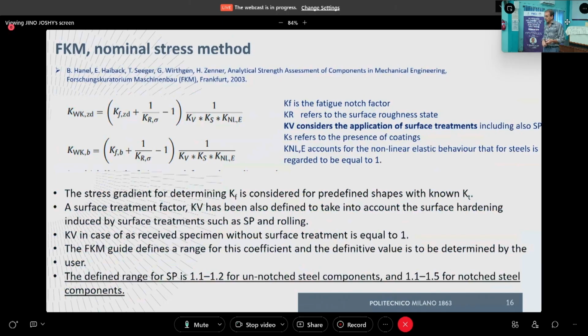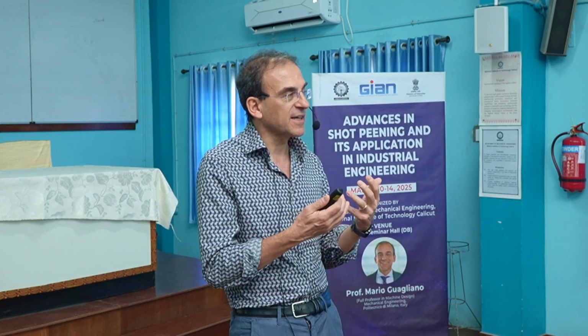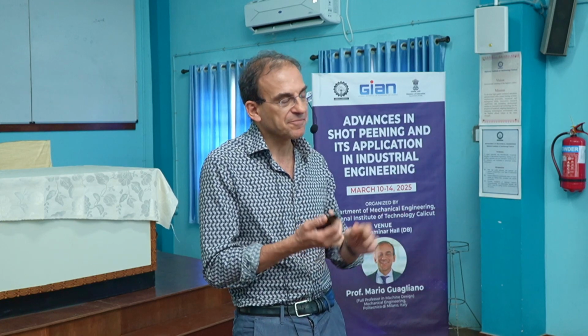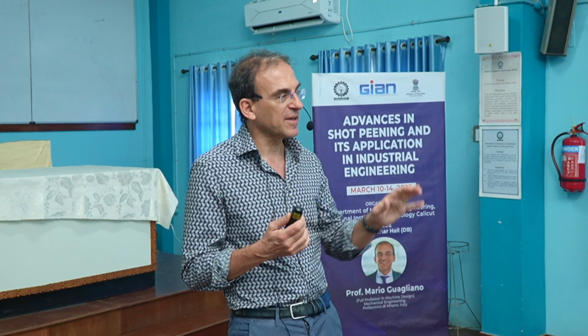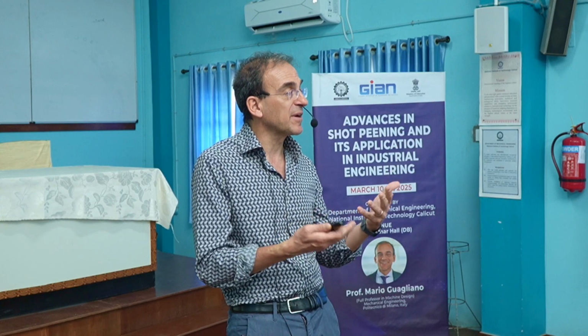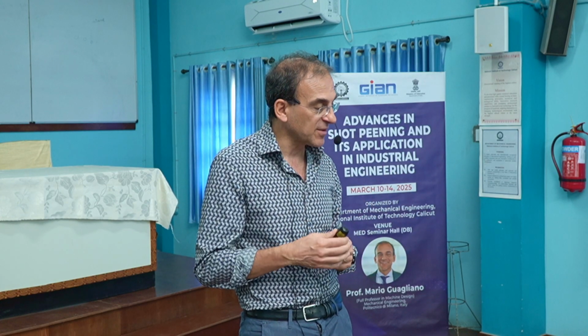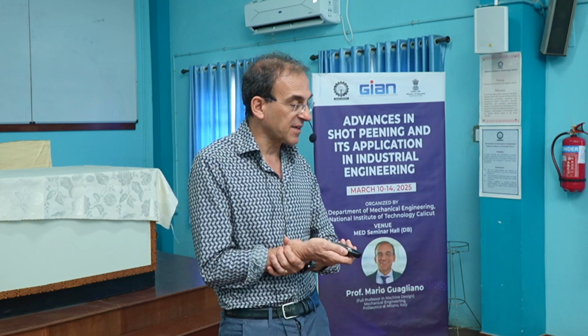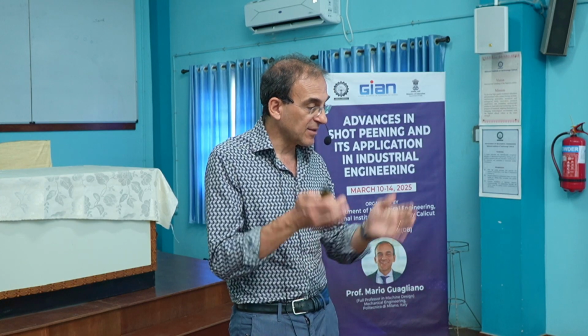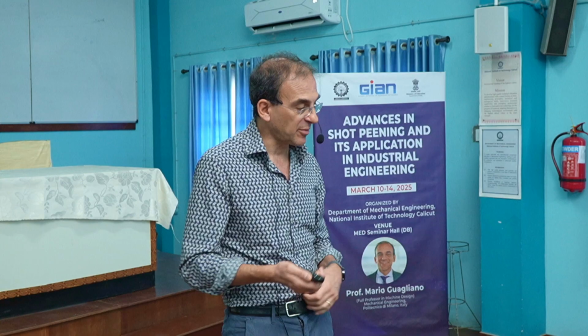The formula reported here is the same. How can we consider the stress gradient? Indeed, we are in the nominal stress approach field now. And so, how can we consider the notch? Only some kinds of notch are considered. That is to say, the nominal stress approach does not want you to make any complex calculation. This is not the aim. They give you some tables and graphs with common notched geometries, and some numbers related to this geometry, in such a way that you can calculate the effect of the stress gradient and the effect of KF. And you must refer to this factor, otherwise the nominal approach cannot be applied.